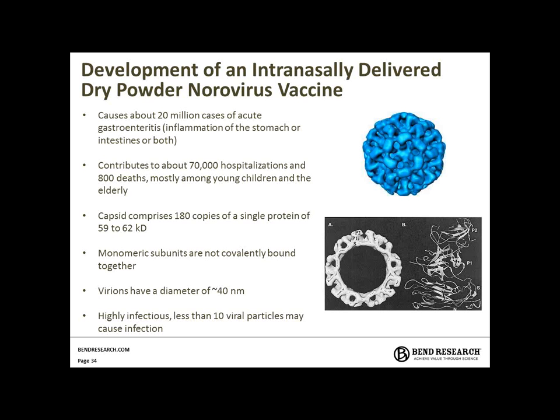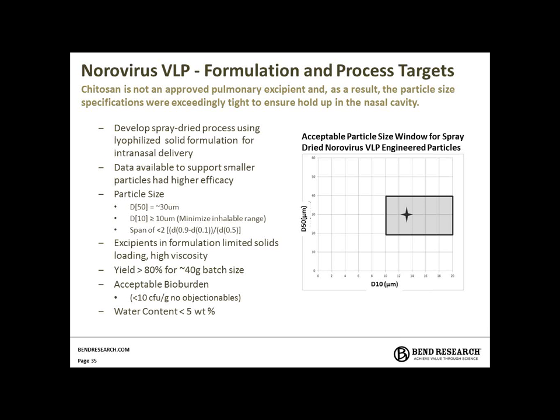The molecule we were working with was a non-enveloped virus-like particle. And of course, there's some other information around the actual norovirus available here. Slide 35 provides the high-level problem statement of developing a spray drying process using a lyophilized solid formulation for intranasal delivery. There was data available to support that smaller particles had higher efficacy, but there was concern on the extreme small end of having the particles be introduced into the lungs. So one of the primary particle size goals was minimizing particles in the inhalable range, shown by that D10 target being greater than 10 microns.